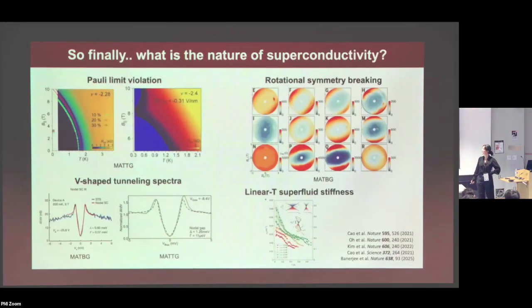Okay, so finally, we can't ignore this question. We've been talking about superconductivity, but what is really the nature of the superconductivity? There have been different types of experimental evidence pointing towards the unconventional nature of this superconductivity, including, we already saw, the critical magnetic field violating the nominal Pauli limit in magic-angle trilayer graphene. On top of that, the STM spectra showed this V-shaped tunneling spectra instead of a flat bottom U-shaped one in these materials. And we also saw this spontaneous breaking of the rotational symmetry in the system in the critical magnetic field direction, which is called nematicity. And more recently, we also saw this linear-T superfluid stiffness, but not going to go into detail. Basically, all of these and many other experiments in the past have been pointing towards a potentially unusual nature of the superconducting gap.